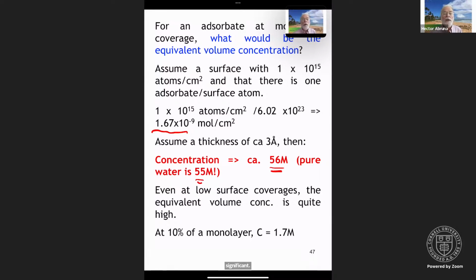It says, where would non-charged inorganic molecules like water fit in? I mean, if it's uncharged, then they don't respond to the field. And if the charge density is low, then basically very little, if any, interaction as a function of the applied potential. However, you can have species that are attracted because of dipolar interactions. And so water can be oriented, the dipole of water, and we'll talk about that when we talk about the double layer, as a function of the potential. If there's zero net charge, then there's really no driving force for that.